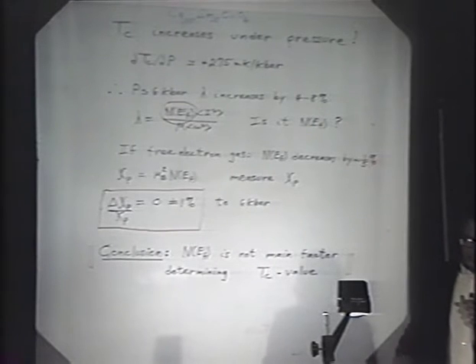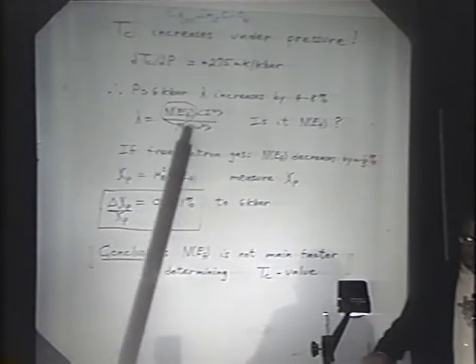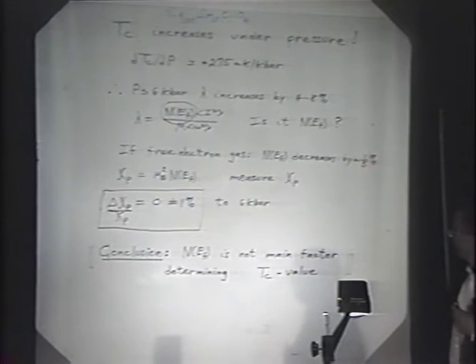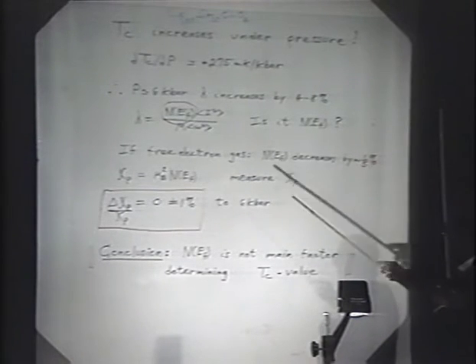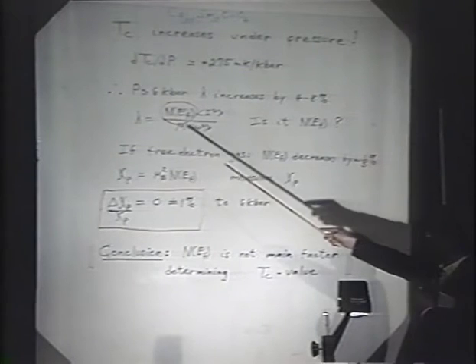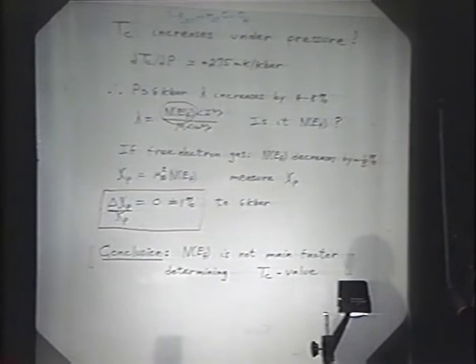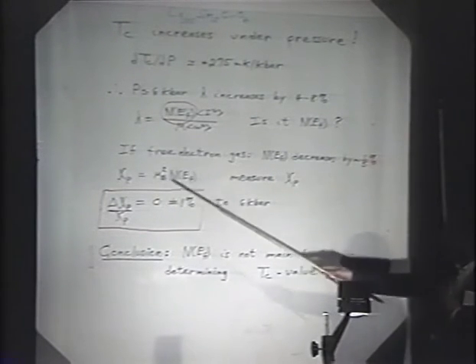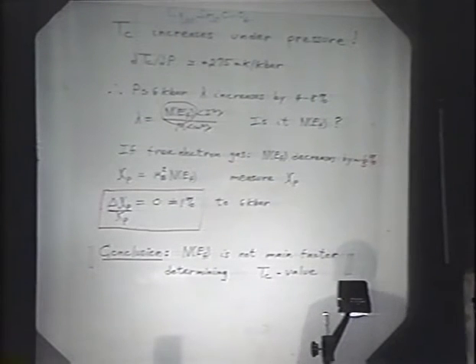All right? Now, lambda would be related to the density of states and other parameters by this well-known formula, so that if the density of states is increasing and is responsible for this increase in lambda, then we would expect to be able to see it if we measure a quantity which is proportional to the density of states, and that would be the paramagnetic susceptibility. So we measure the pressure dependence of the susceptibility and see if it's comparable with the pressure dependence of lambda.